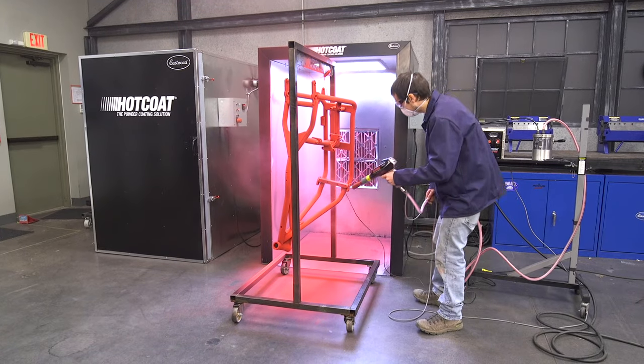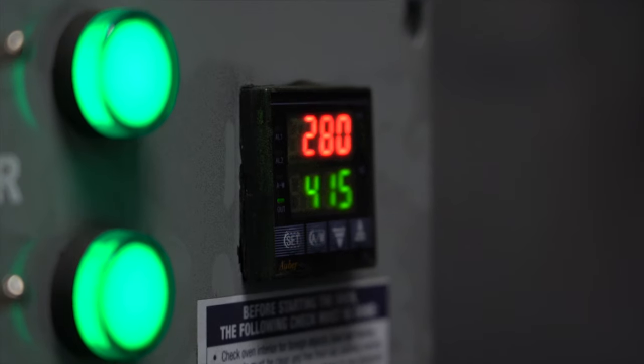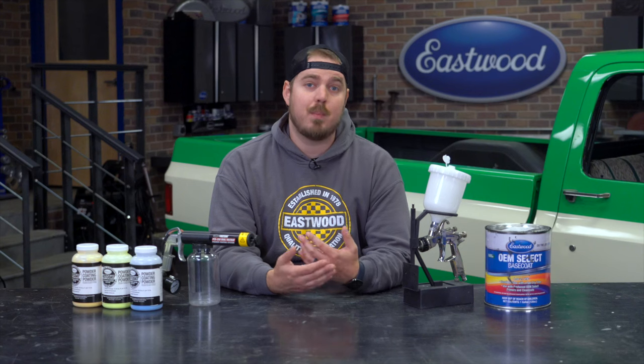This is one of the many reasons you don't see entire cars rolling around with a powder coated finish. Powder coating also has limitations with materials — the piece you're working on needs to be able to withstand at least 400 degrees Fahrenheit because of the baking process. So if you need to coat wood or plastic, you should stick with paint.